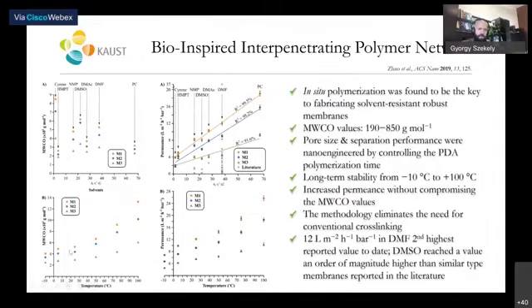And we noticed that with the increase of temperature, the pores are opening up, probably due to membrane swelling. So you get a higher permeance with higher temperature, and at the same time you get higher cutoff, which means that the membrane is actually becoming looser, with the pores opening.